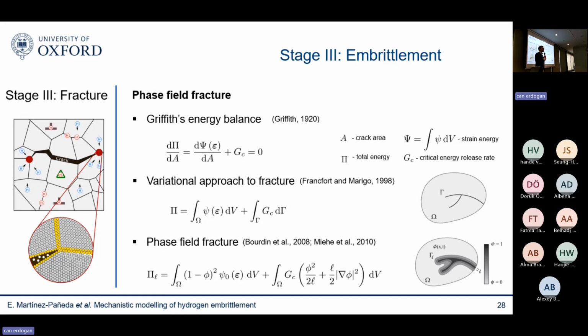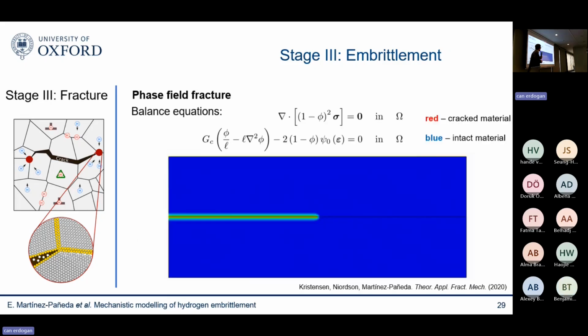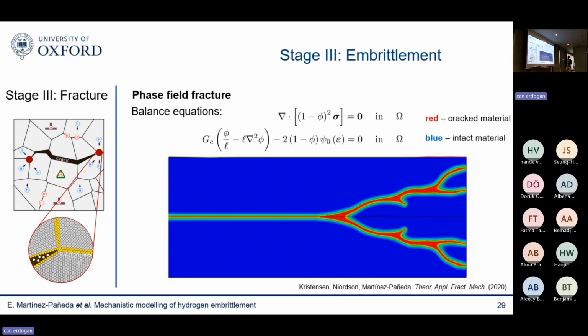And basically, you can see the phase field is a little bit like a damage variable. So you go from 0 in intact material points to 1 in fully cracked material points. It's a little like a non-local continuum damage mechanics model. There's some length scale in there, which makes it mesh objective. Your results are going to be mesh independent if your mesh is fine enough. And then you also degrade, like a damage variable, the load-carrying capacity of the material. And you can get a good overview if you look at the balance equations here. So on the top, you have the balance of linear momentum. So this is the standard equation that you solve in deformation problems with the phase field degrading your load-carrying capacity.